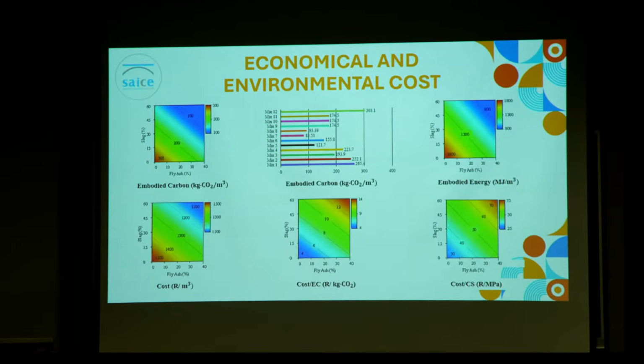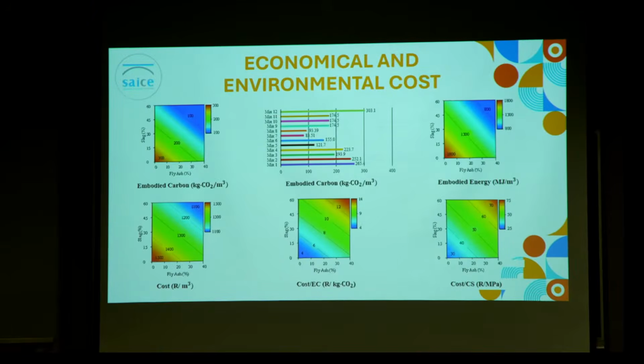Similarly, the relationship between cost and compressive strength shows that both fly ash and slag contribute to concrete performance. As their proportions change, we observe a clear interaction over here in the green region, where approximately 30 MPa can be achieved at a moderate and cost-effective level.